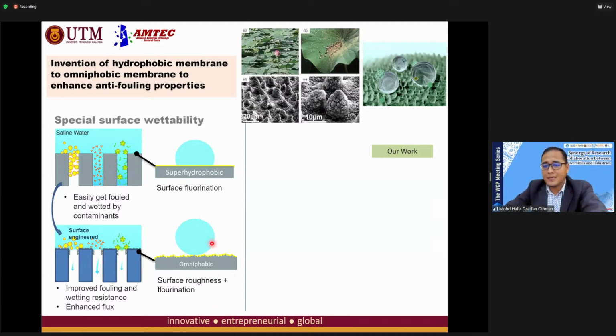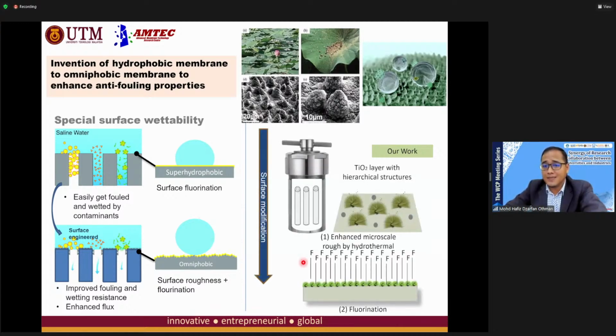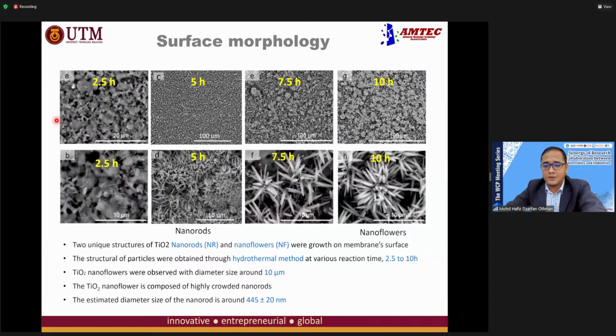We use the same method that we used to produce the photocatalytic membrane, the hydrothermal method, in order to roughen the membrane surface before we do some fluorination on the membrane. So this is the structure of the membrane when we vary the hydrothermal time from 2.5 hours up to 10 hours. We can obtain a nanorod structure at 5 hours and a nanoflower structure at 10 hours. We compare these two structures together with the neat membrane without the coating. When we look at the cross sections, we can see that the membrane with the nanoflower structure has a higher hierarchical structure.